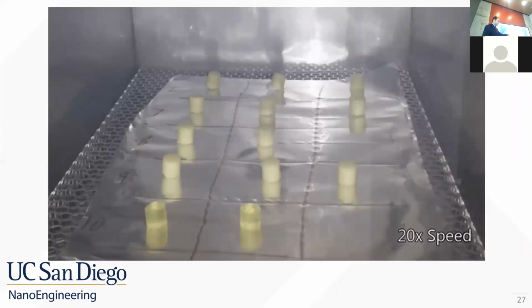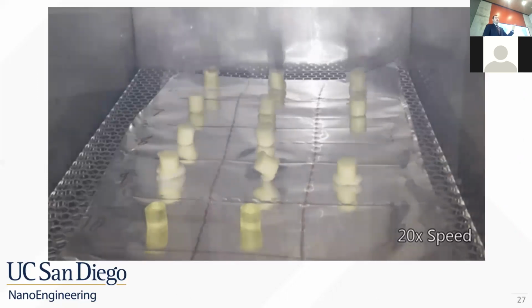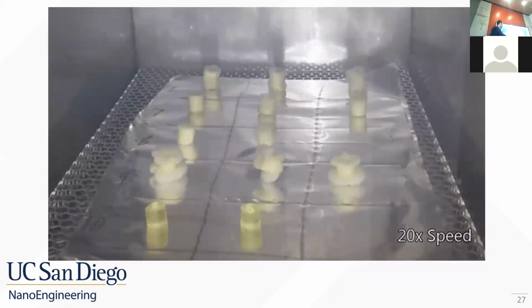Here's a demonstration of this effect. All of these 1 centimeter by 1 centimeter sample cylinders were printed with the exact same chemical composition, except this front wall, which is control.